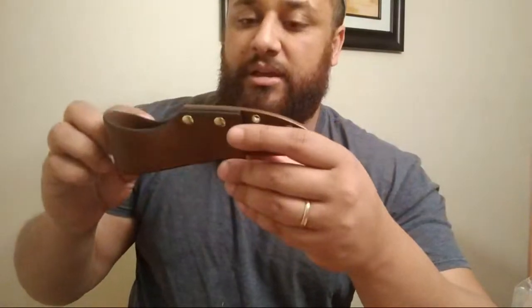Why not a Maxamet collab? Because I felt 15V offered more advantages than Maxamet. The reason why I like 15V better is because it's exclusively vanadium carbide. It's not muddled up with having M6C carbide. At the same time, there's no other steel that has as much exclusive vanadium carbide without anything else mucking up the microstructure. The M6C carbides inside of the Rex 121 kind of clump up the structure and make it larger. You have 24% vanadium carbide, but then the remainder to make up the 32% carbide is going to be M6C, which is a tungsten molybdenum rich carbide.